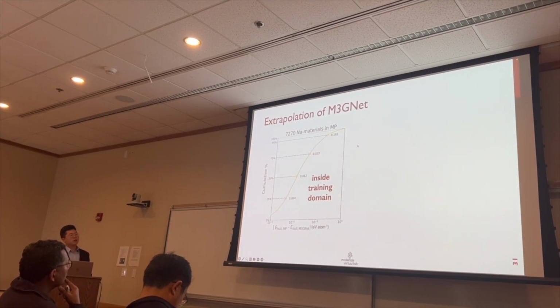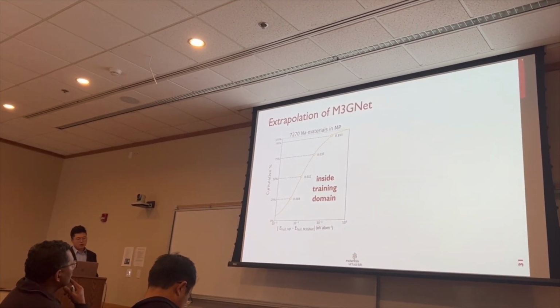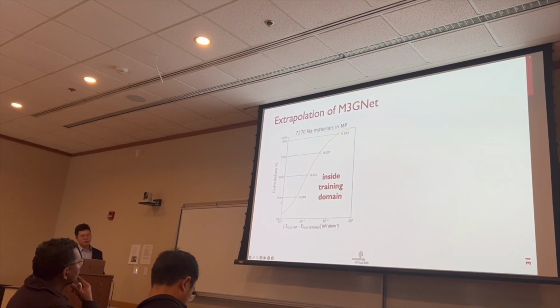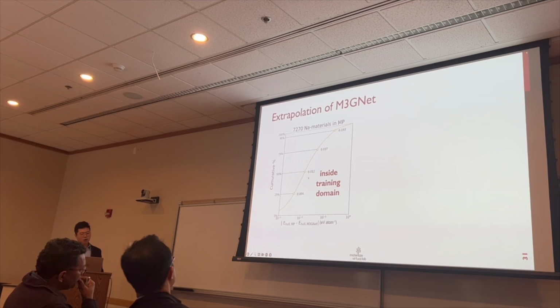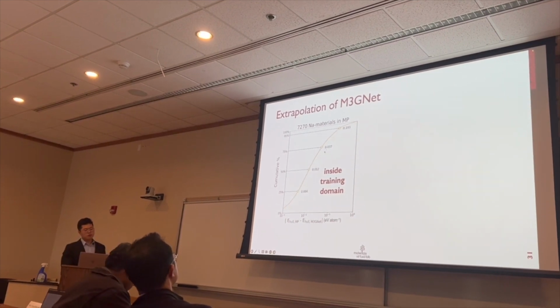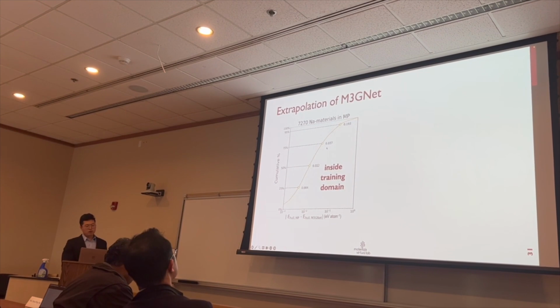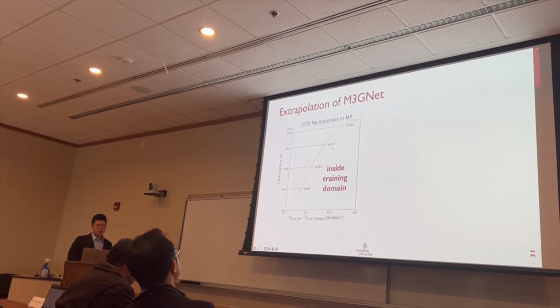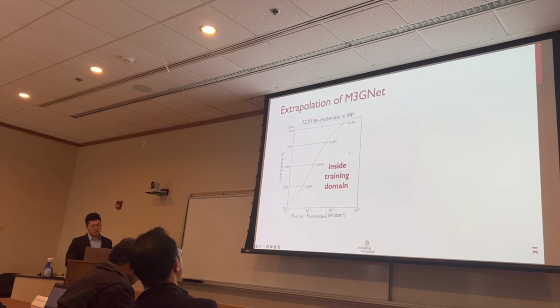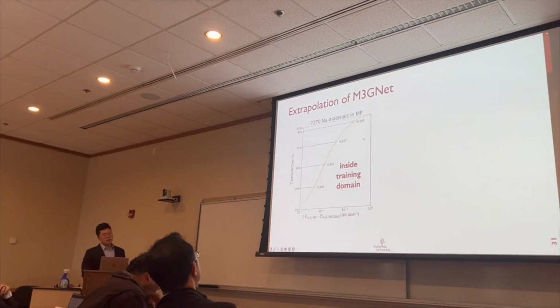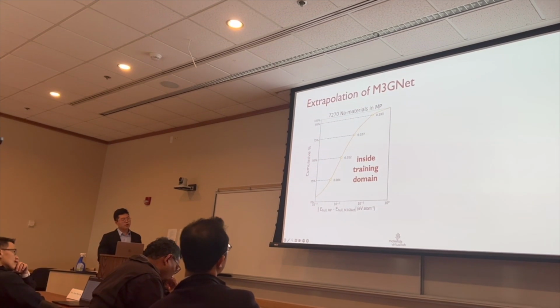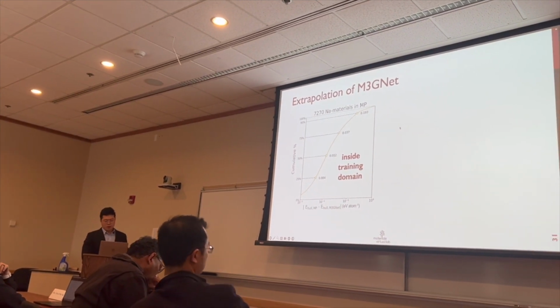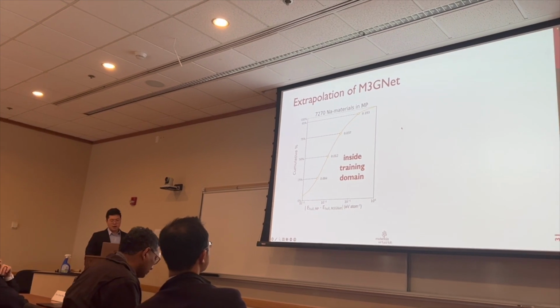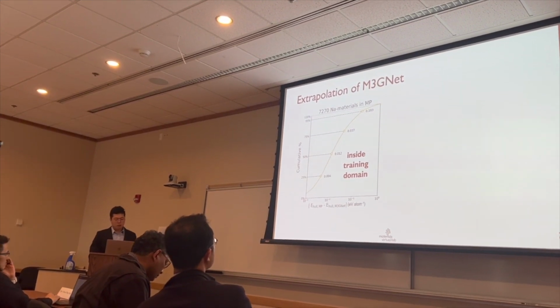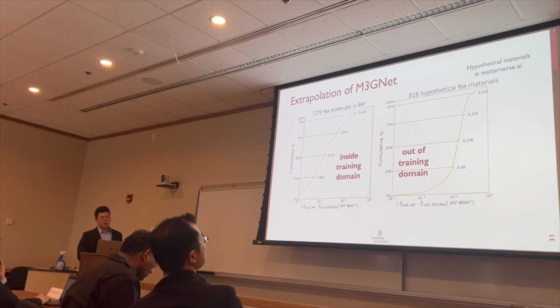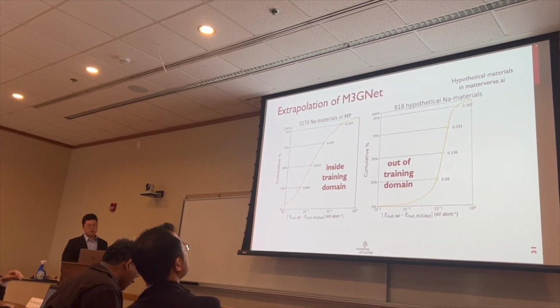7,270 sodium-containing materials in the Materials Project. You can see that more than 75% of the results actually have a very low error of below or equal to 0.37 eV per atom for relaxation energy. So those structures are considered as inside the training domain of M3GNet because they are contained in the Materials Project. However, we really want to test and challenge the limit of the M3GNet model by some extrapolation, that's on the hypothetical materials not included in the training domain.